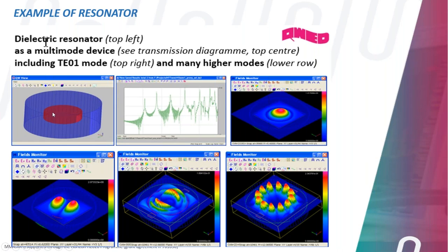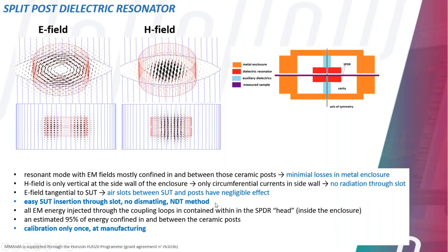Now dielectric resonator, these are simulations from our QWED software. We have a dielectric resonator in a cavity. We excite versus frequency, so the horizontal axis is the frequency axis. And you see that at some frequencies, the response is maximized. So those peaks are resonances. Each peak corresponds to a different field pattern. You will see that the fundamental mode has no angular variation. Fields are constant around the circumference. The second mode has unity variation, so these are magnitudes. So at a time instant, we have maximum, zero, minimum. And further modes may have a higher variation in radial or also in the azimuthal direction.